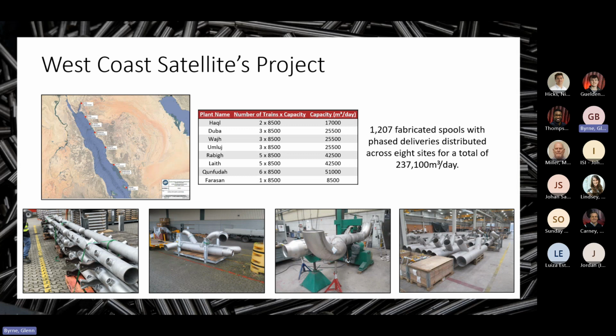This is some information on what we found to be a challenging project that we completed in 2019, and from a logistics point of view, it was very challenging. It consisted of 1,200 fabricated super duplex stainless steel spools with a capacity of 237,000 cubic meters a day. Sets of pipe spools were distributed across eight job sites down the west coast of Saudi Arabia, on the Red Sea coast, and specific numbers of spools were supplied in a phased delivery schedule to each of these job sites to meet a strict fabrication schedule.